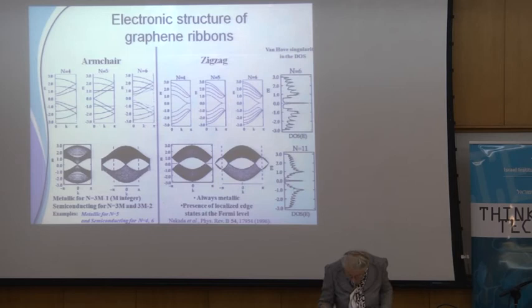And now the important thing that I have to tell you is that the armchairs will have band gaps, but the zigzags never have band gaps. So we can make armchair graphene ribbons with band gaps, and we control the band gaps. If you have a thinner ribbon, then you have a bigger band gap.